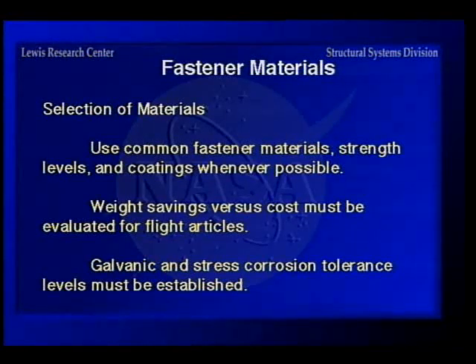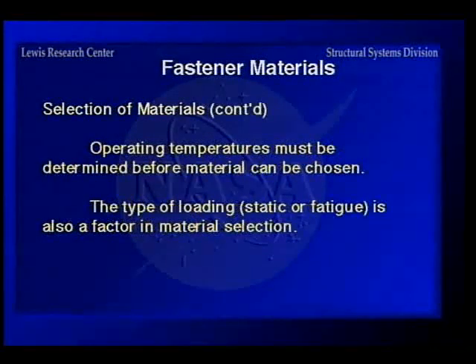You should use common fastener materials, strength levels, and coatings if you can. There's no sense in overkilling on any design because it just costs you money and time usually. Weight savings versus cost must also be evaluated for flight articles, and there you do spend a lot of money to save a little bit of weight. Galvanic and stress corrosion tolerance levels have to be established and checked out. And of course the operating temperatures have to be determined before the material is chosen, both the high and the low, to make sure that the materials are compatible in the entire range. And then the type of loading, static or fatigue loading, is also a factor in the material selection.